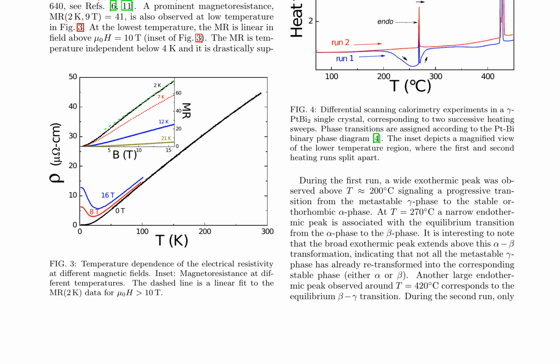Differential scanning calorimetry (DSC) is used to investigate the phase stability of the gamma PtBi2 single crystal. Figure 4 displays the temperature variations of the heat flows during two successive heating sweeps, revealing phase transitions assigned according to the PtBi binary phase diagram. The first run shows a wide exothermic peak above T approximately equals 200 degrees Celsius, signaling a progressive transition from the metastable gamma phase to the stable orthorhombic alpha phase.